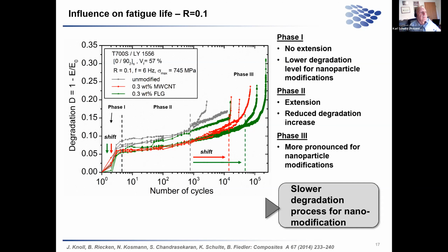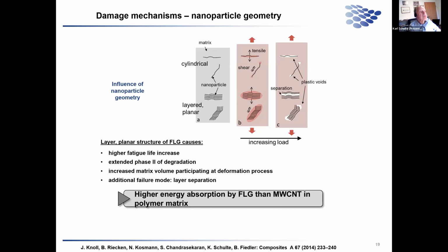So the process behind that, if we have this few layer graphene, is that we not only have bifurcation of a crack and of a crack tip, but with the few layer graphene, they separate - they open here and they form either what we can see here as plastic voids, or they form additional cracks and bifurcations.